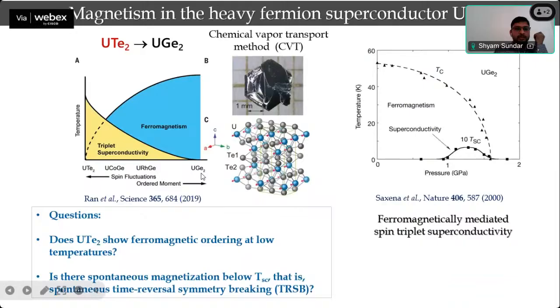Where you see ferromagnetism, it is unlikely to see superconductivity, because magnetism destroys superconductivity. So when people saw superconductivity in these compounds, uranium germanium 2, rhodium germanium, and cobalt germanium, it was very clear that this cannot be of conventional type. And so people were very interested in studying their superconductivity. The interesting thing was that all these materials show ferromagnetic order before showing superconductivity. When people discovered uranium ditelluride, they did not see any magnetic order down to 2 Kelvin, but they saw ferromagnetic fluctuations. So they say that this is the paramagnetic end member of this series.